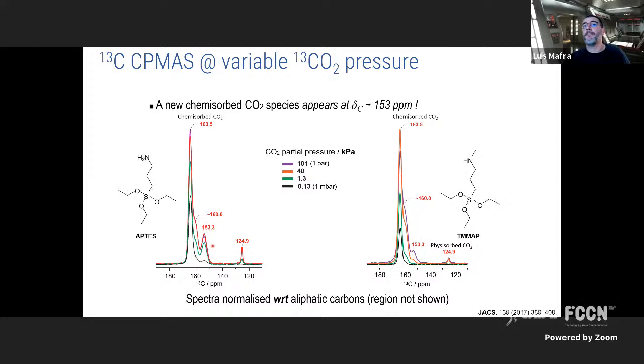You have now a carbon-13 cross-polarization magic angle spinning spectrum. I will not go into details about what it means, but this more or less mimics what you have in solution state NMR. You can see here 2 regions. You see the region of physisorbed peaks, which is about 125 ppm, and you have the chemisorbed region that is on the left side. Okay, so you can really see how the population of physisorbed and chemisorbed species evolve with different partial pressures of CO2.